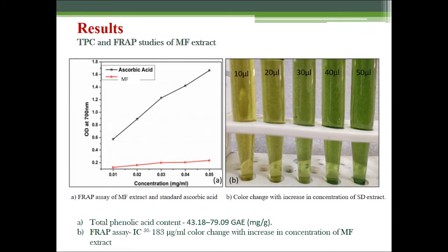The reducing power of the Mussaenda frondosa was evaluated and compared with the standard ascorbic acid. At lower concentration, the Mussaenda frondosa extract had enhanced reducing power capacity owing to its ability to reduce the metal precursor to the corresponding metal oxide nanoparticles and stabilize them. Here the graph corresponds to the reducing power assay, and the picture shown represents the corresponding color change with an increase in the concentration of plant extract.